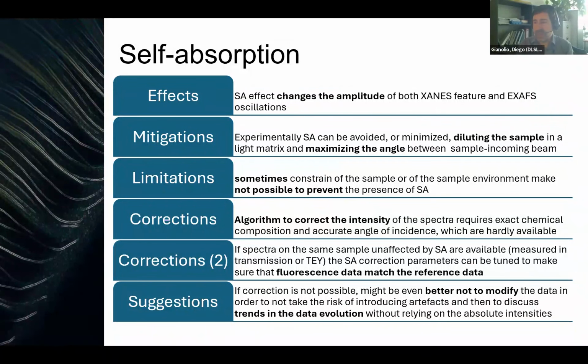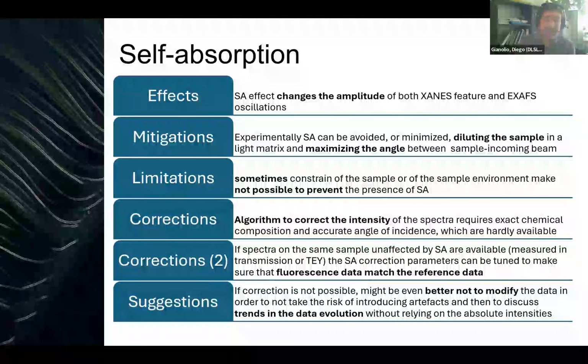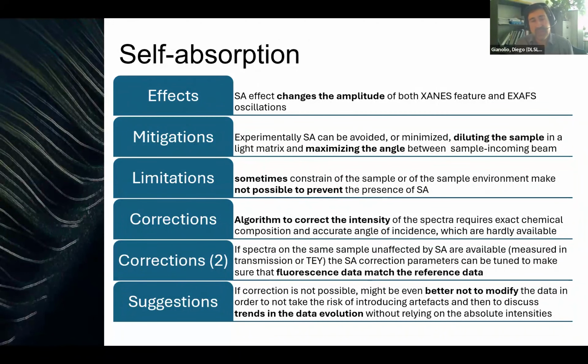And so one of the main problems that I mentioned multiple times in this presentation is really the self-absorption. Self-absorption appears because of, as I said, the change of the penetration depth of the X-rays as a function of the energy during the scan. And this could affect the amplitude of the XAFS oscillations in a nonlinear way. So of course there are mitigations. There are ways to try and avoid it in the data collection, so doing it experimentally, or at least minimize it by diluting the sample in a light matrix, or maximizing the angle between the sample and the incoming beam, so measuring more in grazing geometry.